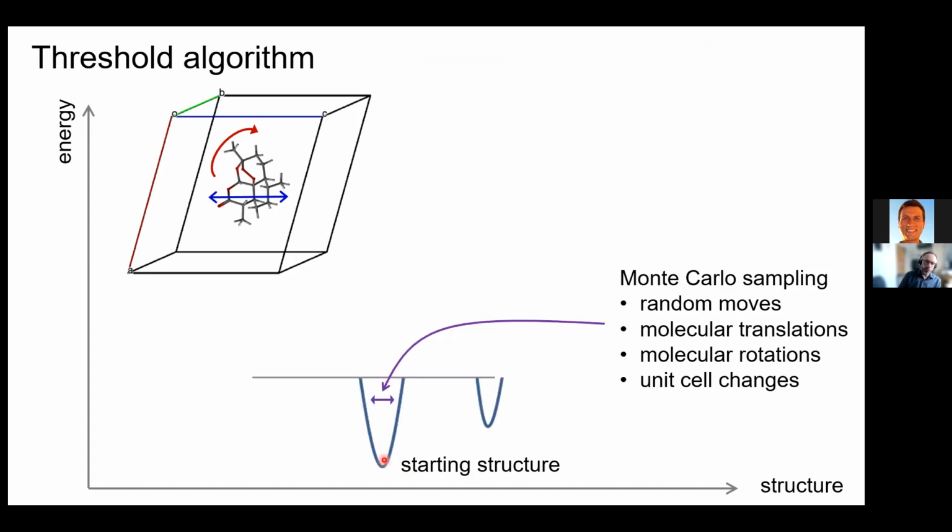And then what we start to do is we increase that lid. All right, and as we increase the lid, then we start to allow Monte Carlo moves within a wider range around that minimum. You see that a little bit of the other landscape has appeared over here in terms of visualization. We can't get to that yet, okay? Because we're only allowing moves which go within here, within this basin, okay? We will only be able to see that energy minimum when the lid starts to get to the point where it goes above the energy barrier that connects these two minima. Okay, so you can see where this is going.